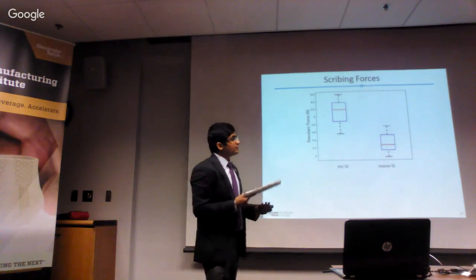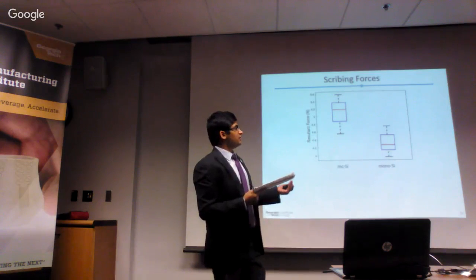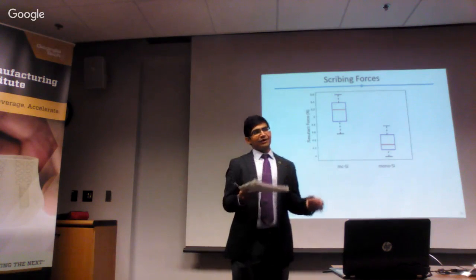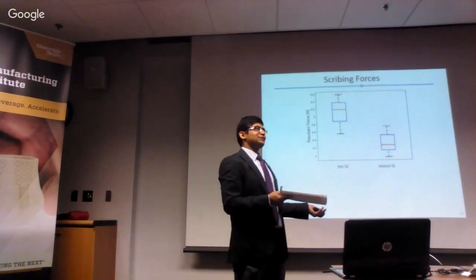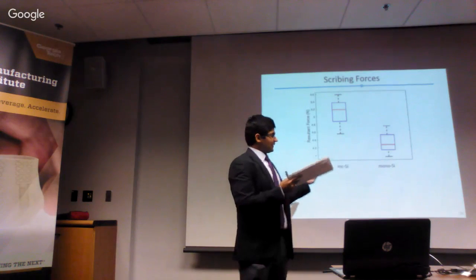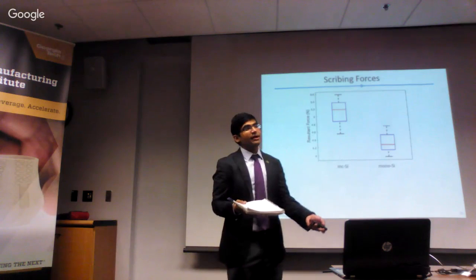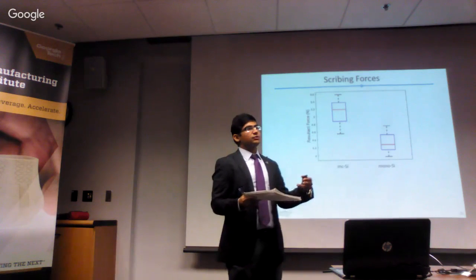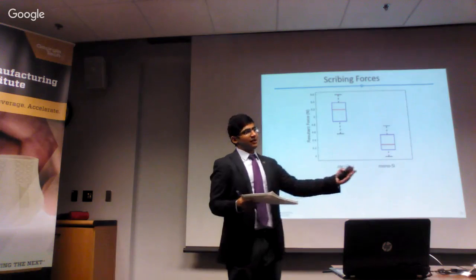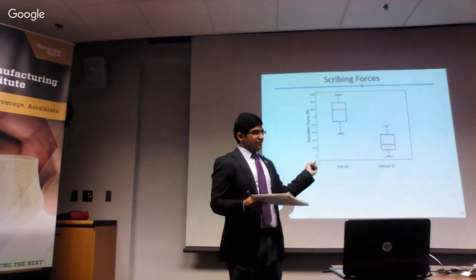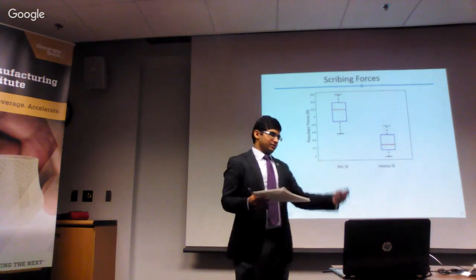I see. So in this experiment, as I mentioned, the focus was on the wear of the abrasive and not on the surface morphology of silicon. The depth of cut was 10 microns, and at that depth the fracture was pretty much consistent across all. So the phenomena you're reporting before is at the lower depth, at 250 nanometers.